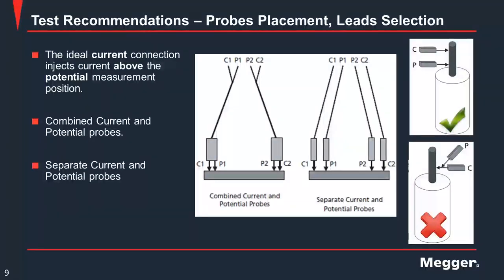position of the probe, this is obviously a wrong method, because what happened in this case is actually the potential probe will measure the resistance on the current probe. So maybe you will get an inaccurate result, because the voltage drop also measures the resistance on the current probe.